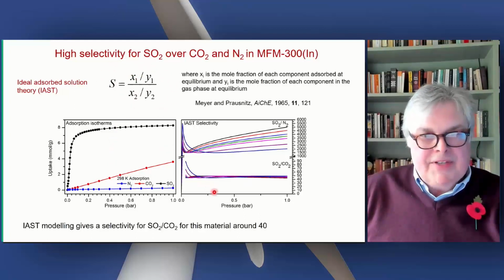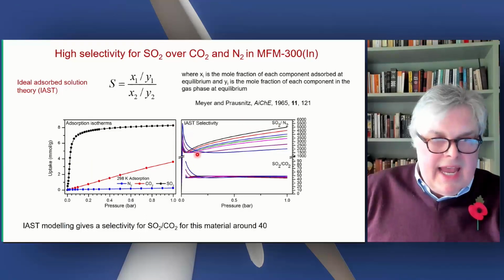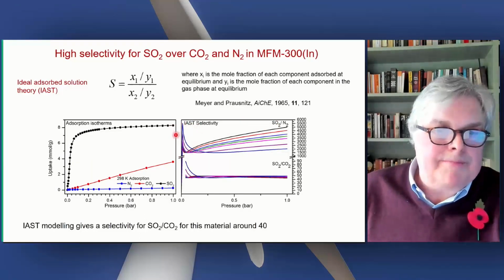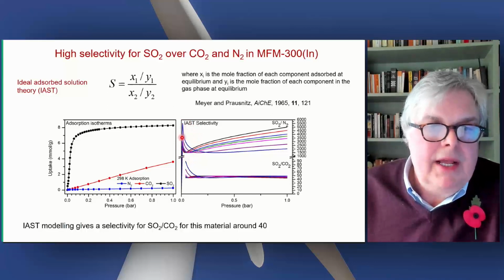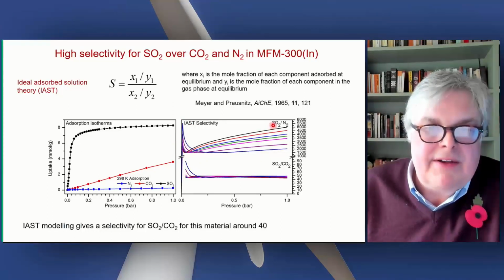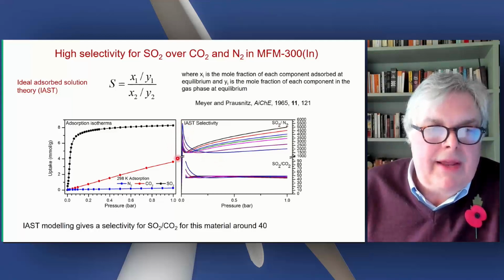And I wanted to emphasize this. You can get analysis of SO2 CO2 selectivity, and you can see this is around 40. But remember, SO2 dinitrogen, you can see there's quite a lot of variation here. As you change the pressure, the selectivity changes. This area is actually not really very accurate, because when you have a substrate that is very strongly bound with a substrate that's very weakly bound, in this case SO2 and dinitrogen respectively, there are a lot of errors at this end of the plot.